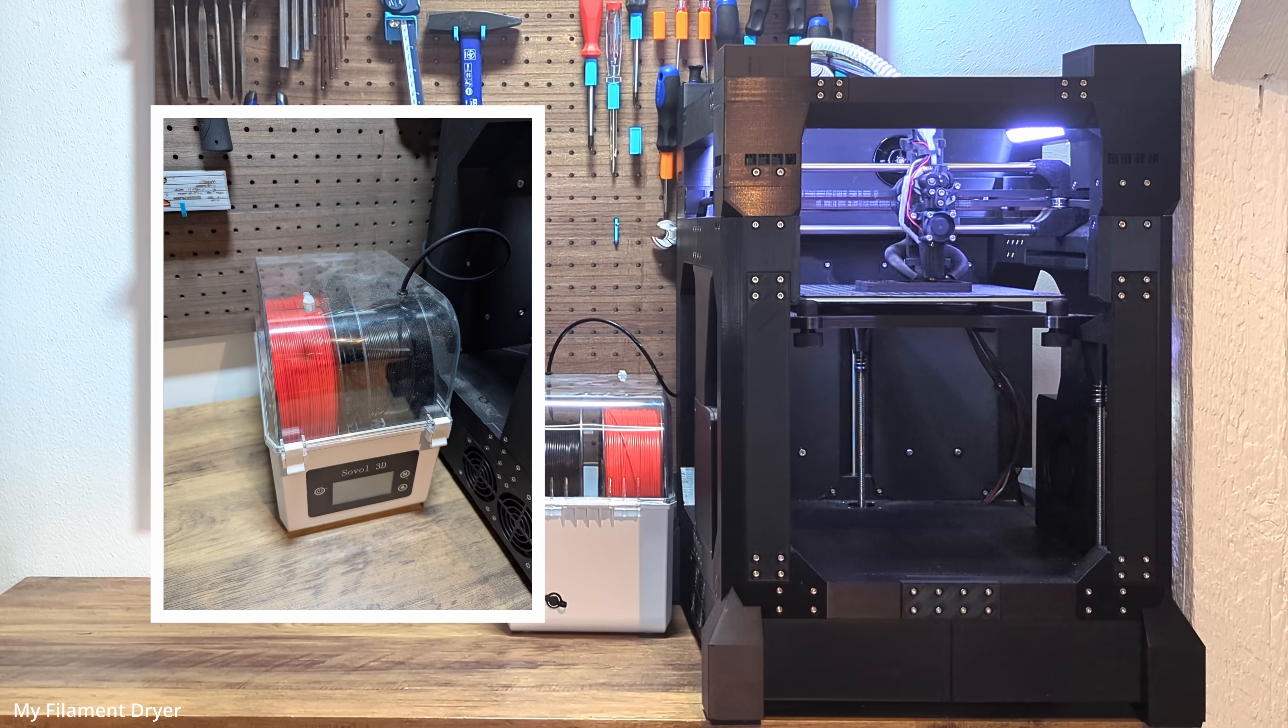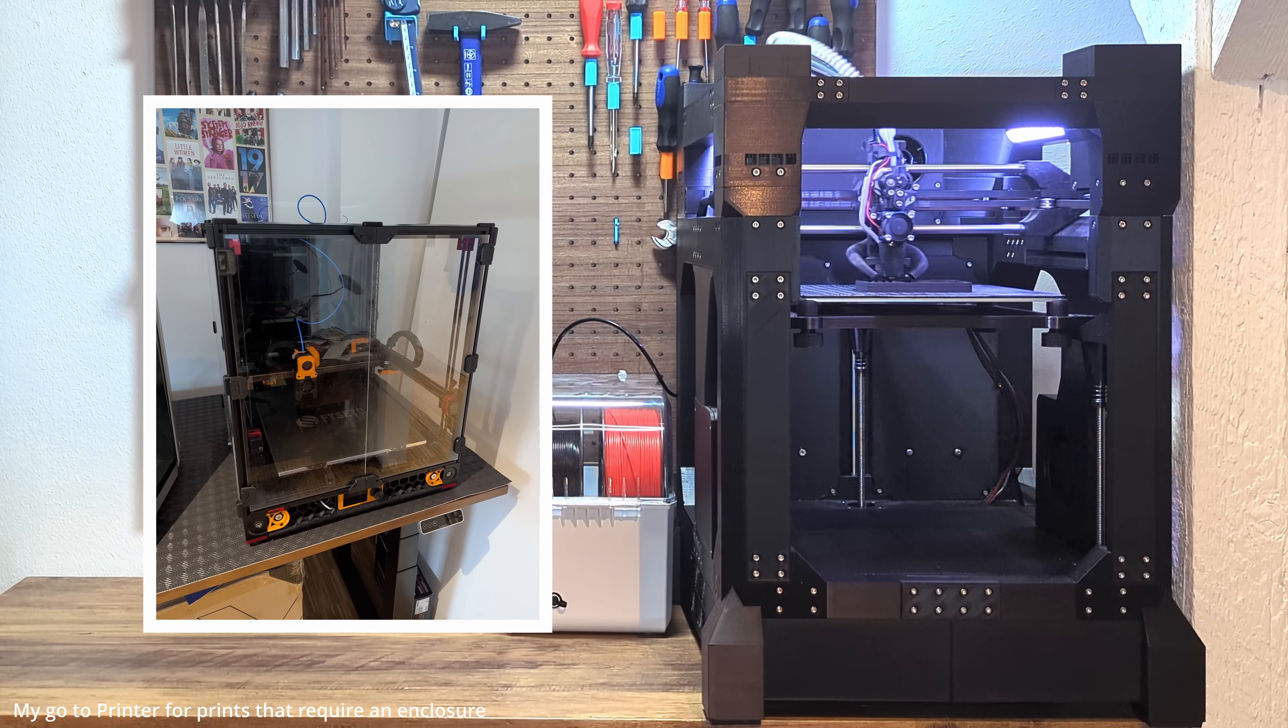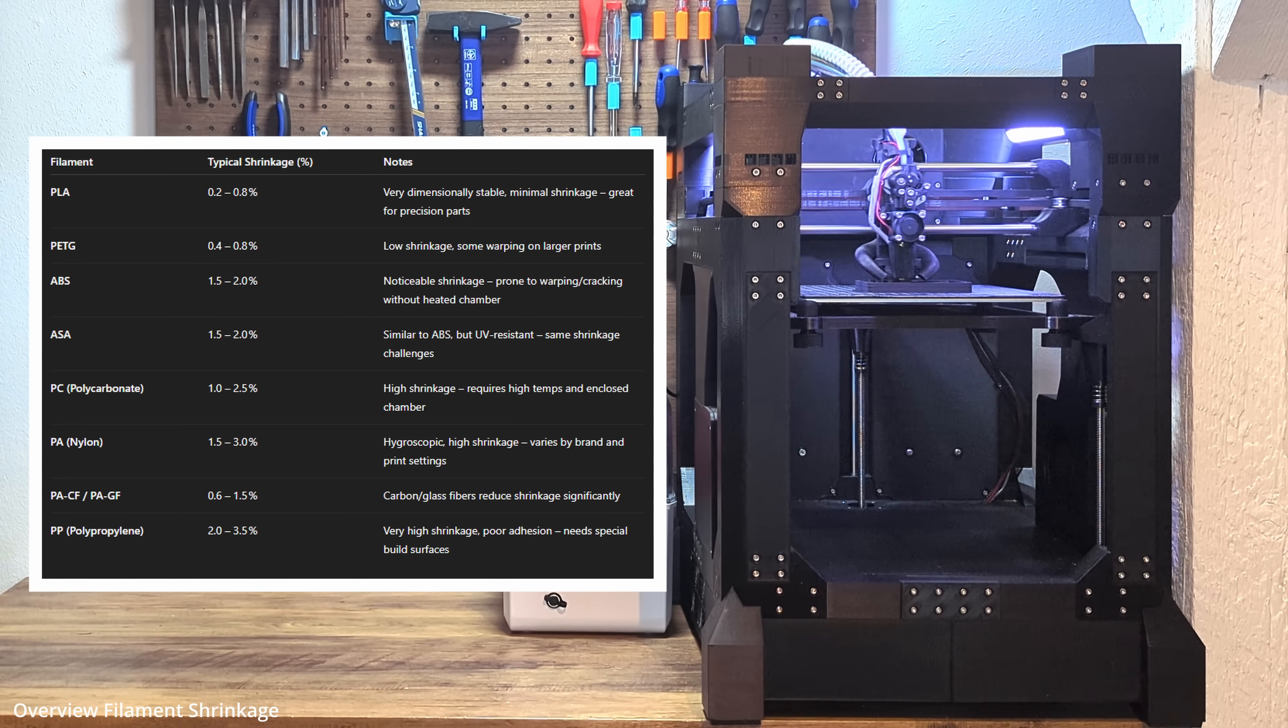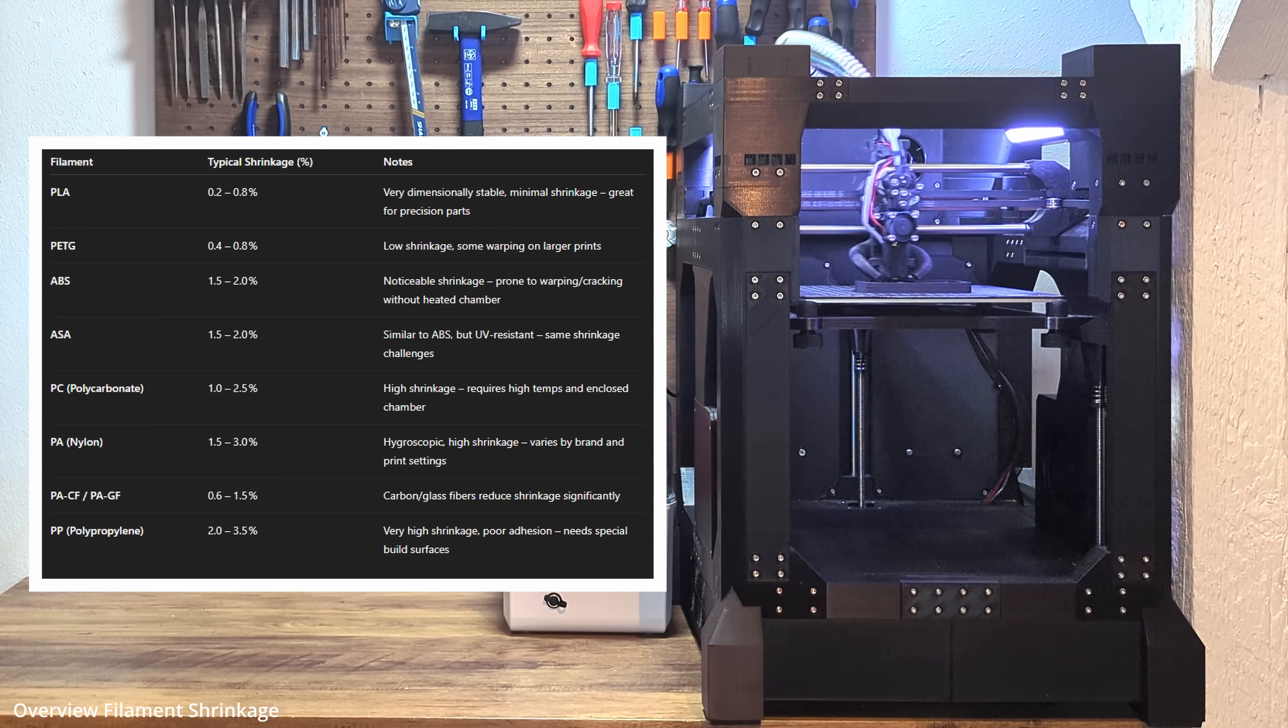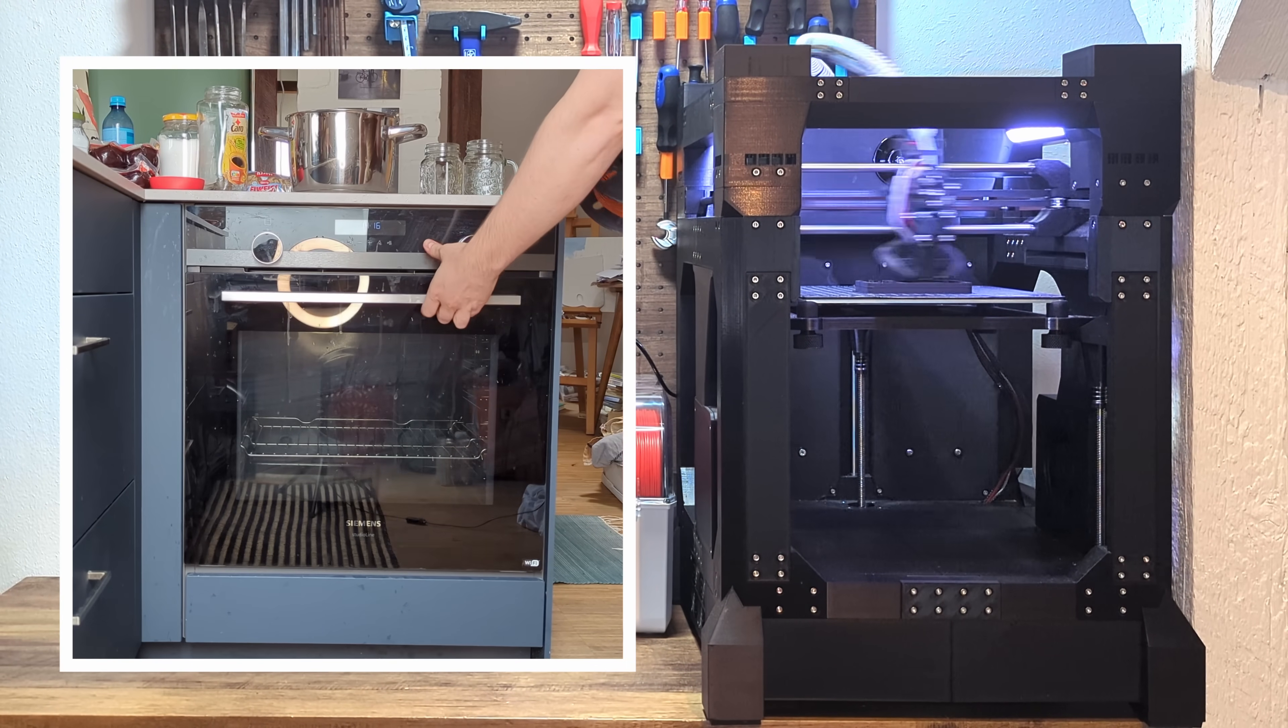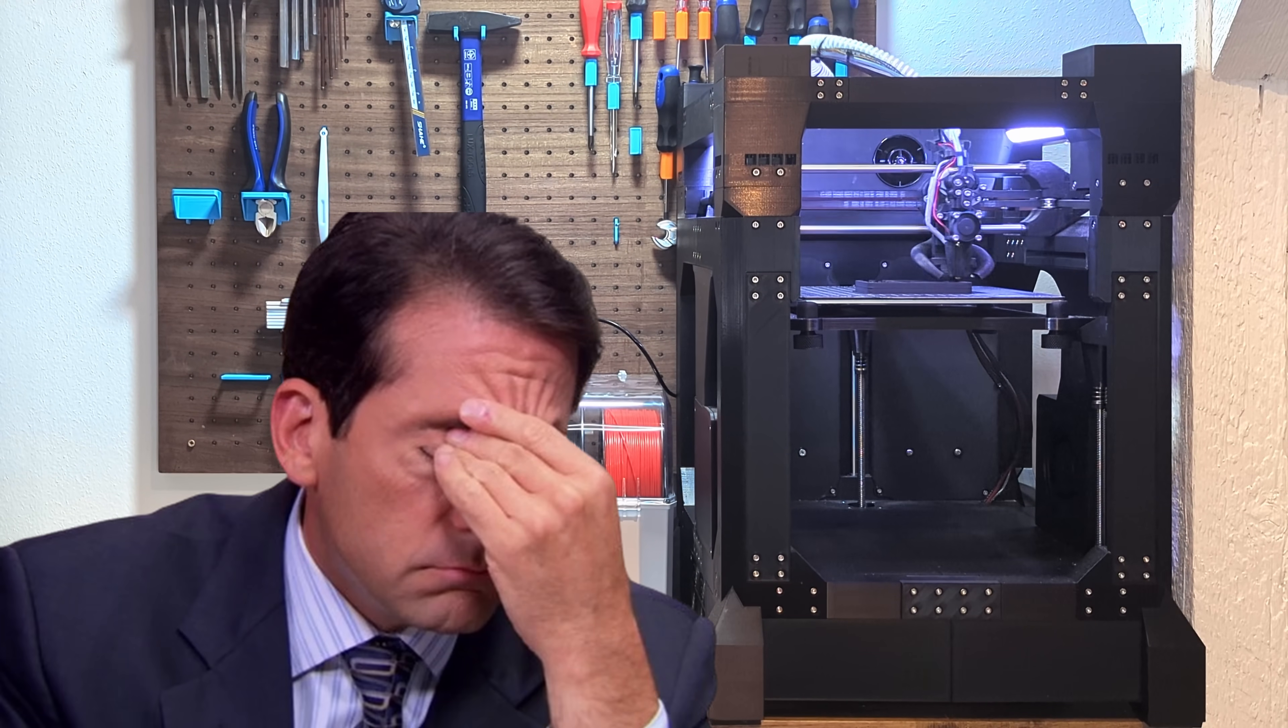On top of that, nylon shrinkage is a real problem. Unlike PLA, your part dimensions will shift if you don't compensate for it. So, I had to reprint the carriage and the extruder parts multiple times just to get them dimensionally accurate. Every morning started the same. Dry the filament in the kitchen's oven for five hours, squeeze maybe two or three good prints, then redry for the next batch. So, yeah, nylon is annoying to print.